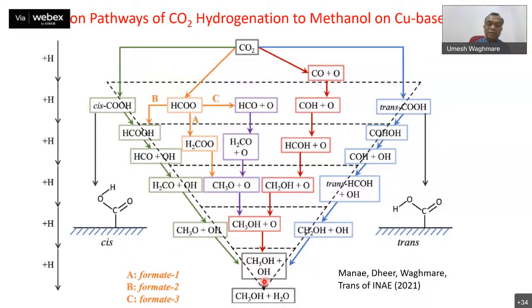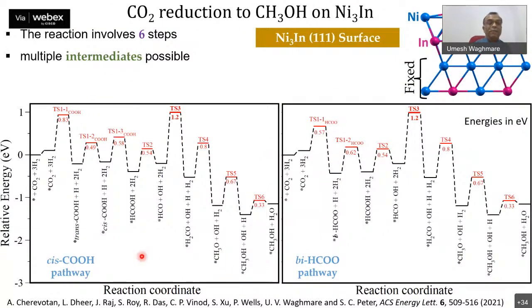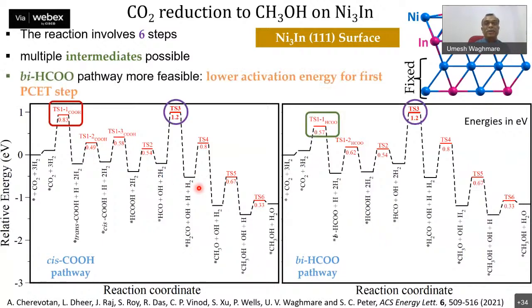And that's where we also leverage machine learning. But the kind of diagrams we can get from the standard model calculation is we look at the surface of, say, nickel indium, consider various possible steps, and then determine the activation energy barriers for each step. And what we could show is, for example, although this is the transition state which has a high barrier, the rate limiting step happens to be TS1, where this pathway is favored because it has a much lower energy than the carboxylic pathway. So this forms a starting point in going about engineering this catalyst further to improve its performance.